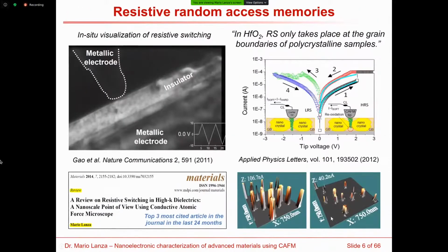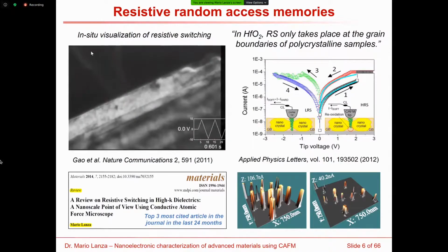So first, let me show you one brief example of what is resistive switching. Resistive switching is a property of some insulating material that when they are placed between two metallic electrodes and one potential difference is applied between them, you can change the electrical conductivity of this material. Here you can see one example. I have the two electrodes and the dielectric, and when I increase the potential difference between them, I can see that the conductive filament is being formed and destroyed depending on the polarity of this electrical field.